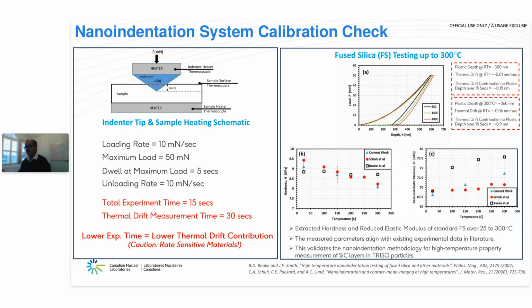Here, the message from this slide is that we tried to do these experiments fast. When I say fast, they're not exactly very fast, but they're still 15 seconds. And based on the discussion that I had here about the thermal drift measurement at different temperatures and the relative contribution, in terms of depth, from drift to the total plastic depth and the influence on the measured properties, the faster you do the experiments, the lower the thermal drift contribution is.